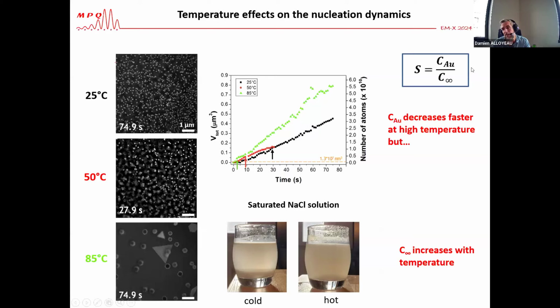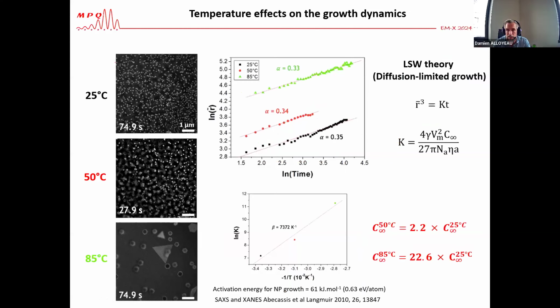So now we have to think about whether the equilibrium solubility of the solution depends on temperature. And the answer is yes. You just have to do this very simple experiment with salt. You put salt in cold water, you have a lot of salt residue. If you are above the equilibrium solubility, you heat up your solution, and you see that you have much less residue because the solubility increases with temperature. And it's also the case with chloroauric acid. So how can we quantify this change? To do that, we analyze the growth rate of the nanoparticles. So here what you see is the evolution of the radius of the nanoparticles as a function of time.